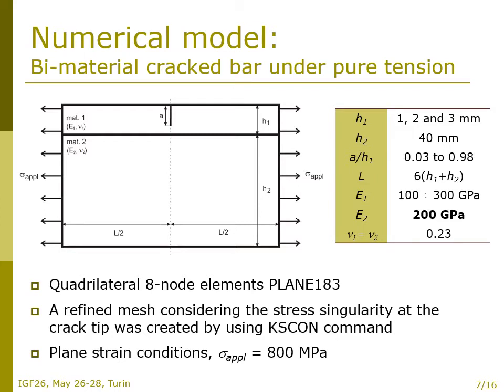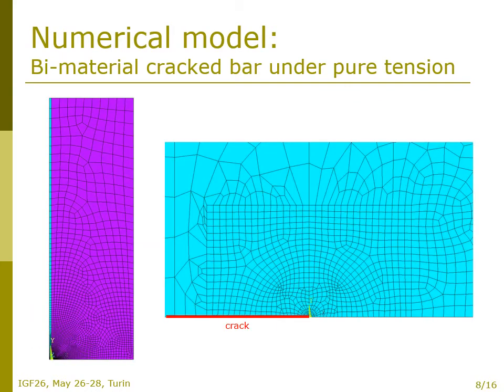In the finite element software, quadrilateral 8-node elements were applied. They are called PLANE183 in ANSYS. Of course, a refined mesh considering the stress singularity at the crack tip was created and plane strain conditions were applied. The material was subjected to pure tension of 800 megapascals. Here you can see the finite element mesh, first in the whole specimen on the left and then near the crack tip on the right side here.